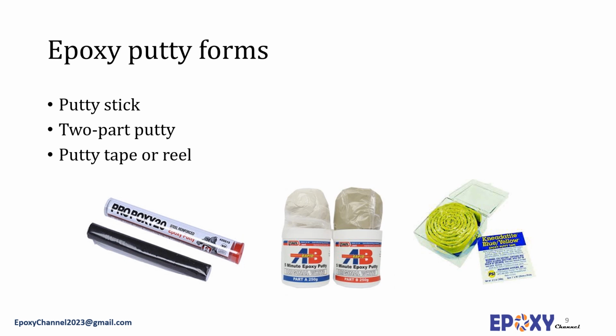Generally, the initial cure rate is 8 to 10 hours at 25 degrees Celsius. It is possible to adjust the curing time depending upon the climate conditions, because the cure speed of the epoxy putty is impacted by the heat. Putties with long working times are more suitable for warmer climates. One alternative format is the epoxy putty tape or reel. The two parts are combined in one easy-to-store reel, and just like with the stick, the required amount of putty can be cut off and kneaded by hand.